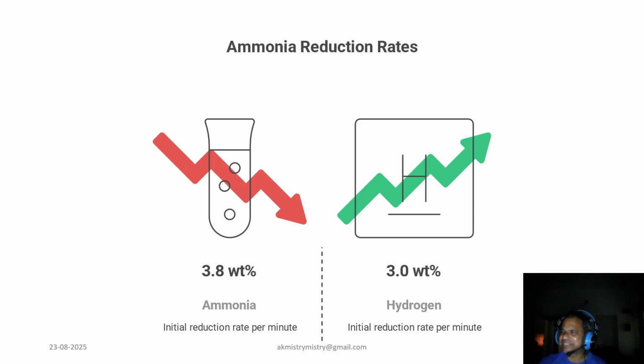As we can see on this slide, which shows the ammonia reduction rates. When comparing efficiency, ammonia reduction rate presents an interesting picture. The initial reduction rate per minute for ammonia is 3.8 weight%. In contrast, for hydrogen, the initial reduction rate per minute is 3.0 weight%. This comparison indicates that ammonia can offer a faster initial reduction rate.